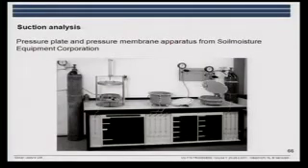The advantage of this is that you can apply it on a virgin, non-dried sample. The problem is that it's time consuming. And often it's also difficult, you place your sample on clay membranes, and they are not always that durable. So it's a difficult test to make. But it can be done, and it is done. Here you see such a setup where we have the pressure plates, different types depending on which pressure they are to go up to.